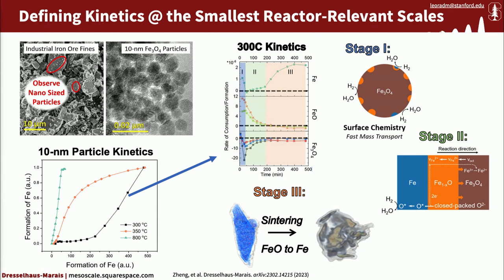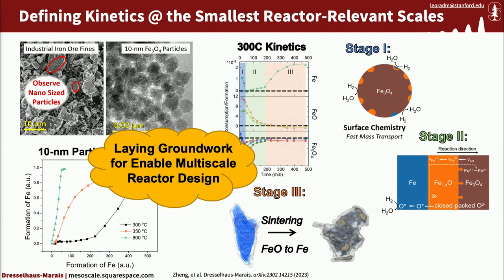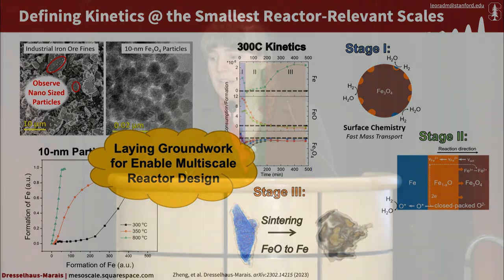As that happens, we were able to demonstrate with this 3D tomographic imaging how the nucleation and growth of the iron phase actually couples to the sintering of the particles at this small scale, causing them to increase in length scale by 100-fold. Even though we started with 10 nanometer particles, who would care at the gigaton scale? So what this really shows you is the beginning of a long-term body of work that we're doing in my group now, laying the groundwork to enable this type of multi-scale view of the process, to be able to link and connect the dots between the scales that have often been overlooked and the full reactor performance.